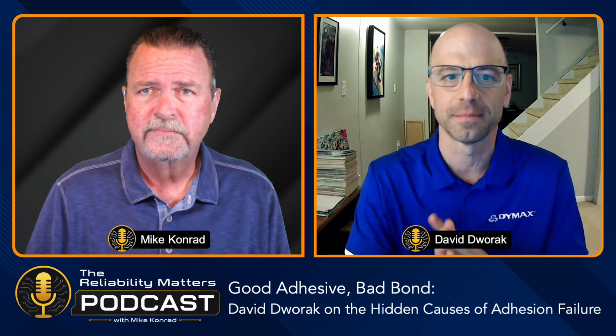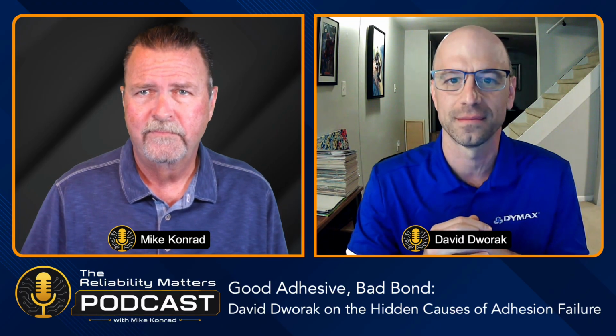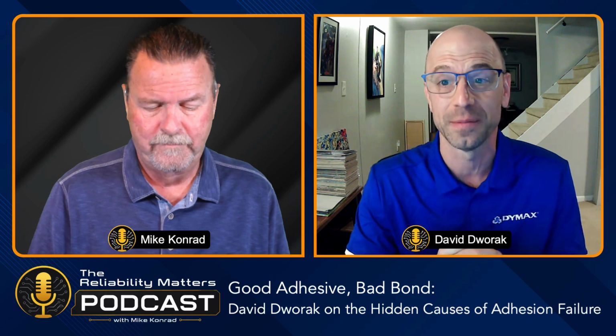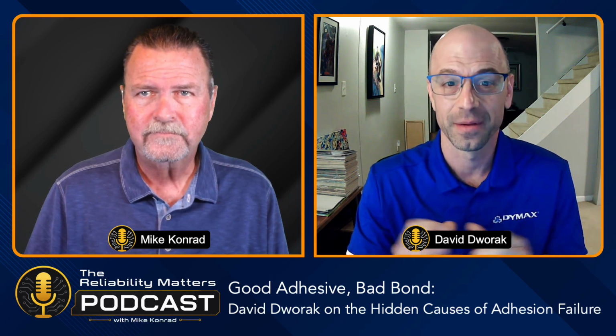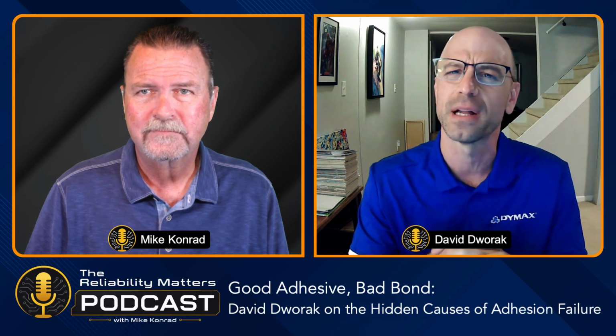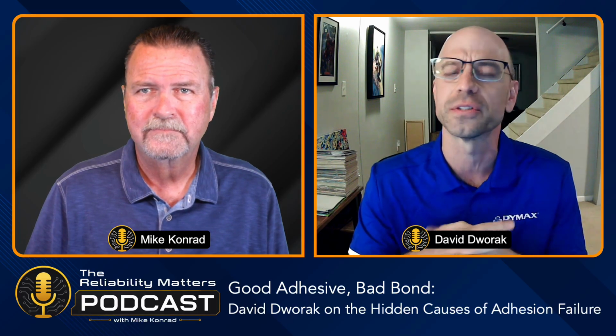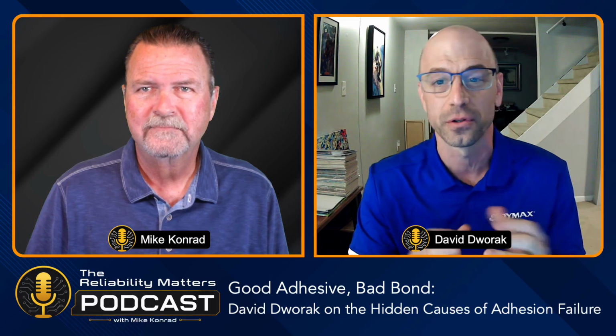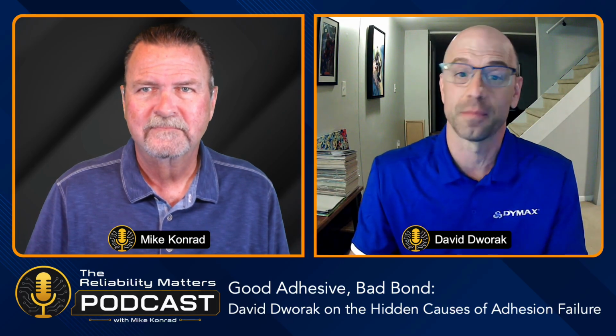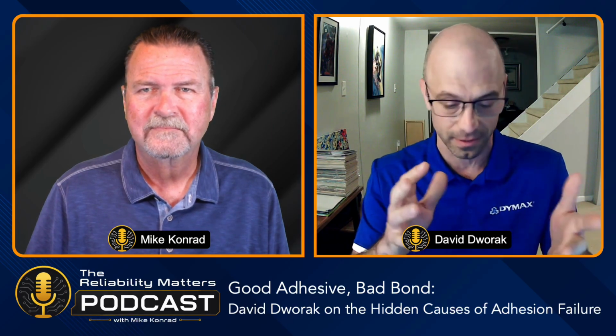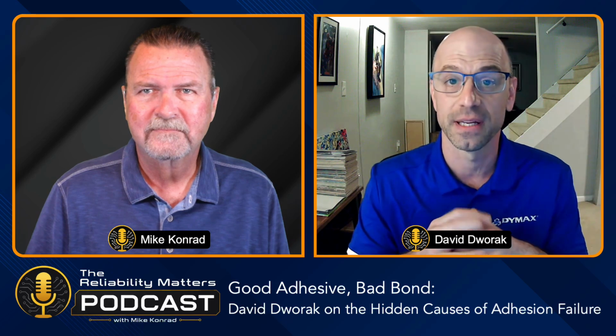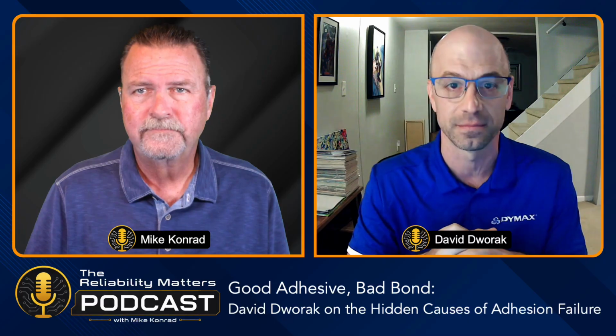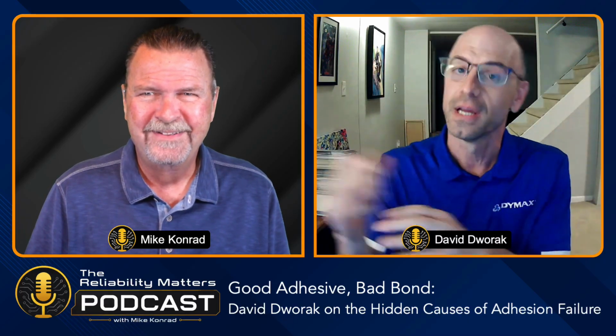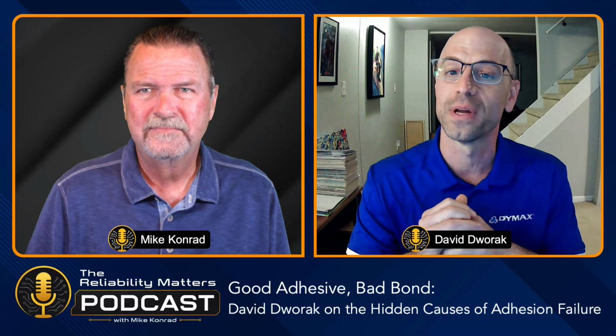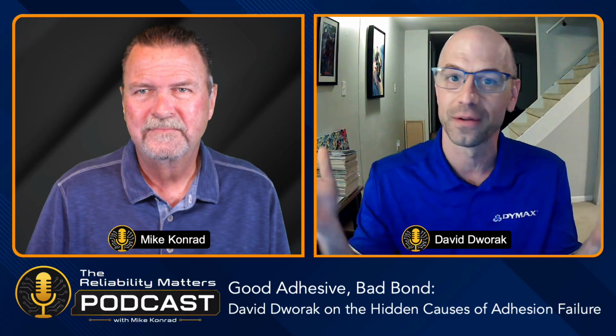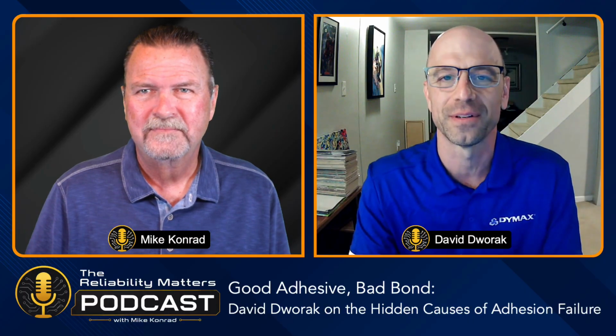So, going back to Teflon and polypropylene, you can clean that all you want. You can use IPA and soap and water, but you're still going to have difficulty bonding with it because of its low surface energy. All right, but maybe you cleaned. Let's take another substrate. Maybe you had some polycarbonate that you're bonding, and you cleaned it really well with some industrial soap and water, and you're still getting poor performance. Well, there could be a surfactant residue on the surface which can disrupt bonding, or maybe you cleaned your parts to be bonded and allowed them to sit in a staging area, and over on the other side of the room there's an aerosol spray system, and the air draft is blowing over, and now it's depositing onto what you thought was an already cleaned part. Well, now you've got a thin layer of whatever was being sprayed settling onto your parts, and you now have a contaminant that you didn't know about.